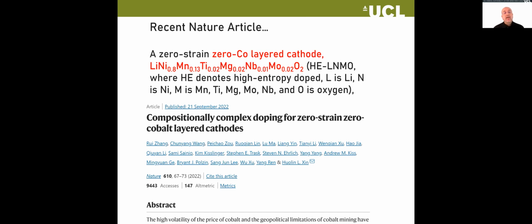And I've seen there's a lot of interest in these high entropy materials, for example. So these nickel, manganese containing materials, by doping in other elements. There's been a lot of literature about how you can dope in elements to improve properties. Often if you're doping into a cathode, such as a nickel, manganese, cobalt layered cathode, these dopants can act as a pillaring effect and stabilize the structure, which means it doesn't form a rock salt structure, which is a less electroactive or not electroactive phase.